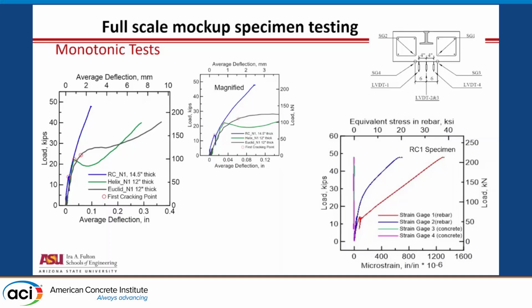Because in the reinforced section, yes, you have the rebars, but it takes nothing for a crack to grow from this. When it forms at the bottom at the tension, it takes nothing for that crack to run from this to this. And this is just a number 6 rebar over 2 feet or so. So there is no way the load is going to be transferring to that rebar effectively. It stays in the concrete because of the stiffness and it cracks. And that crack is clearly shown in here that the response is dropped. Now, basically the rebar is still elastic, even if you go to about 50 kips. So this is a purely elastic design, which is so expensive.